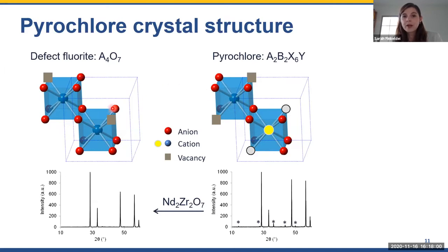And this order-disorder transition, from an ordered to a disordered structure, is particularly of interest if we are thinking about putting a zirconate on the B site, because those materials are known to undergo this order-disorder transition as a response to irradiation. And you can see when you look at the X-ray pattern that the pyrochlore is a superstructure of a fluorite structure, which is indicated by the superstructure reflexes marked with an asterisk in an X-ray.